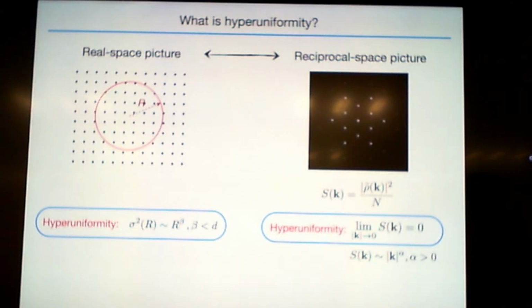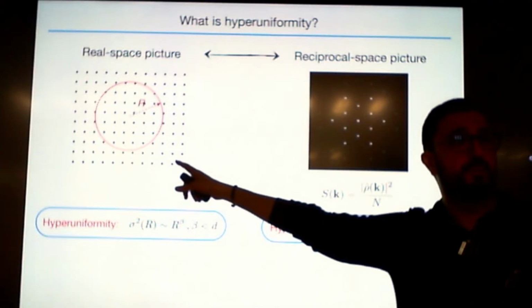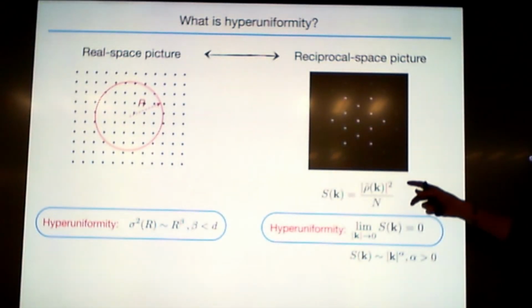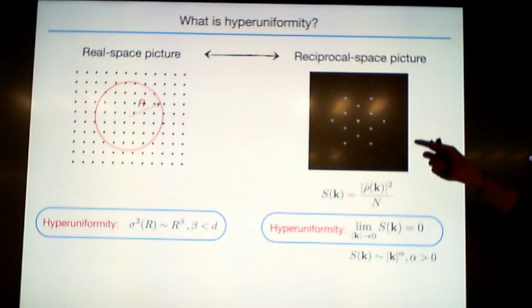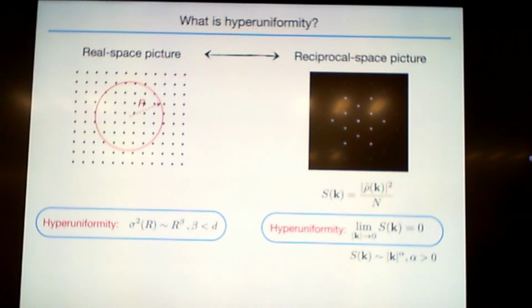So, as you can imagine, in many contexts it is better to look at the structure factor because, especially experimentally, if you do atomic or molecular experiments, you don't really know where your atoms or molecules are. So what you do is scattering experiments, and then you measure the scattering intensity, or the structure factor. Then you can tell something about the system, right?